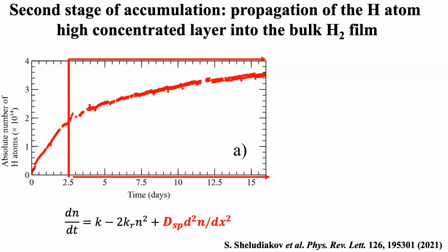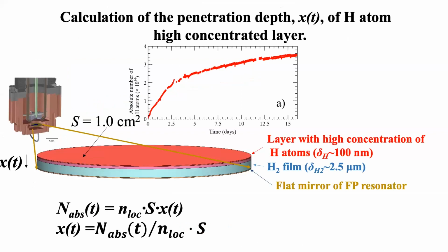Next, we think that at the next stage, the increasing number of atoms is due to propagation of this high concentration layer into the bulk. This diffusion, according to the second Fick's law, is determined by this term of the equation, and here is how we can extract this diffusion coefficient.